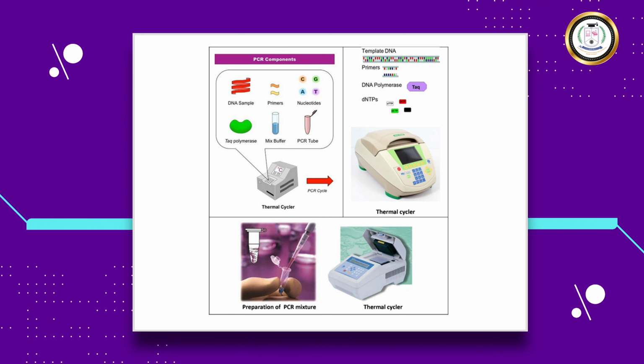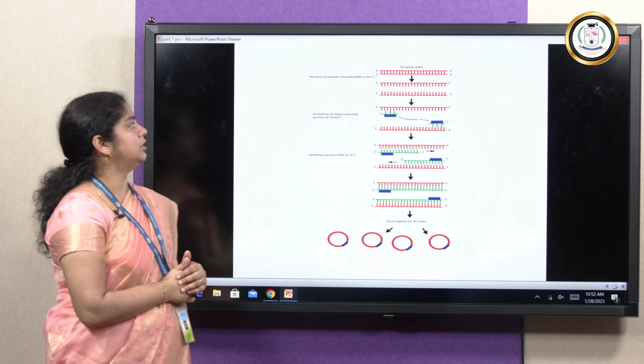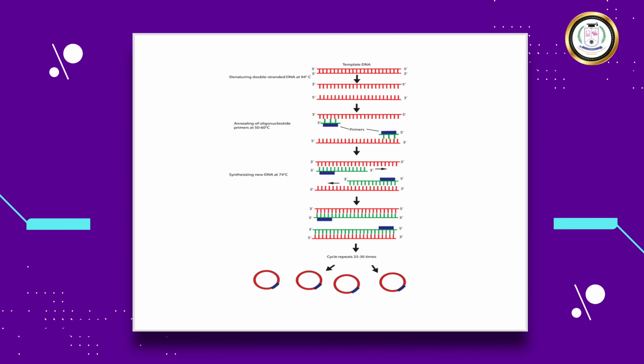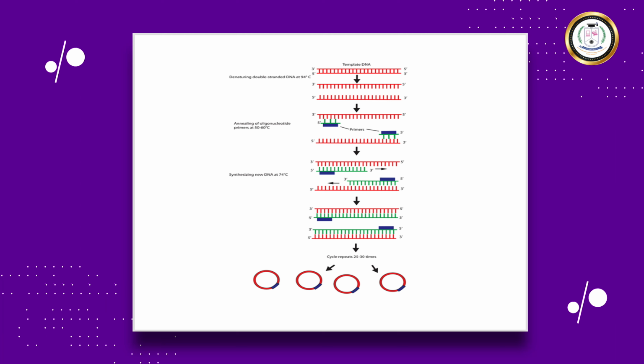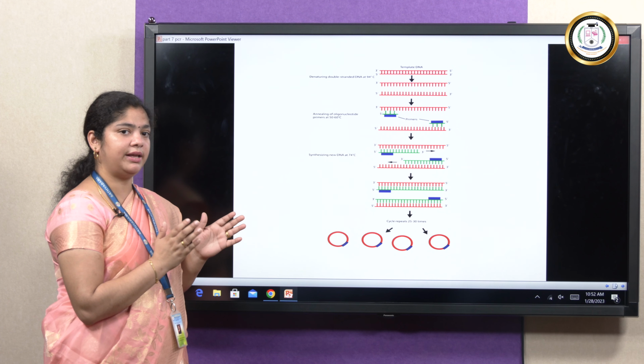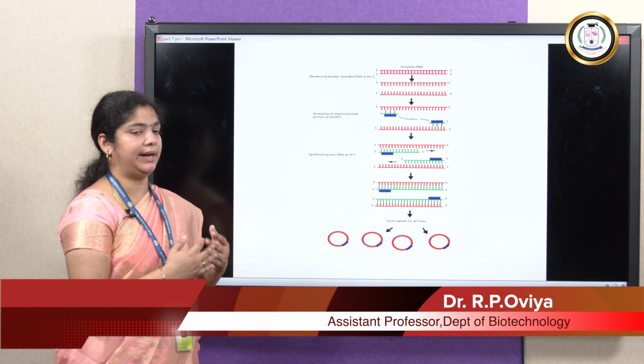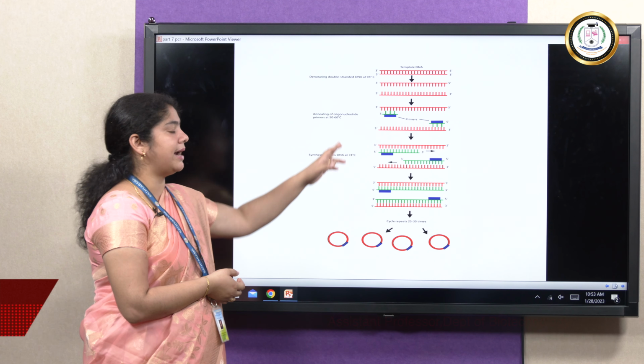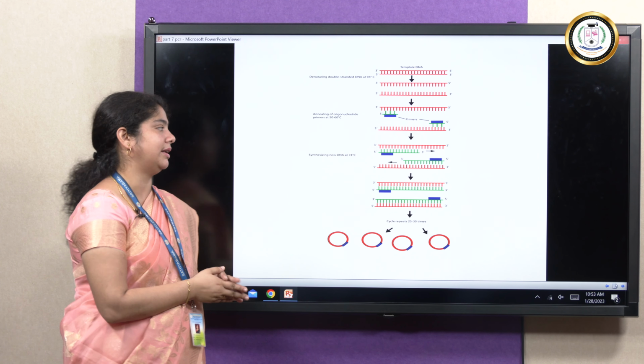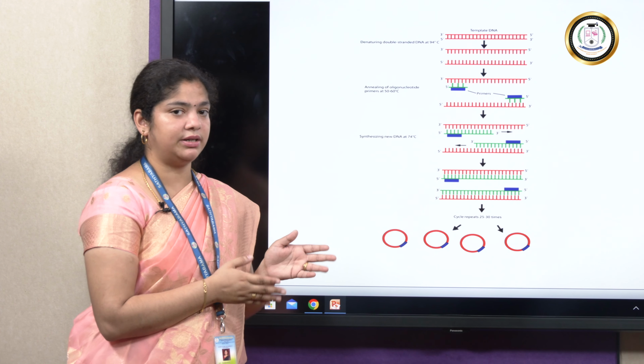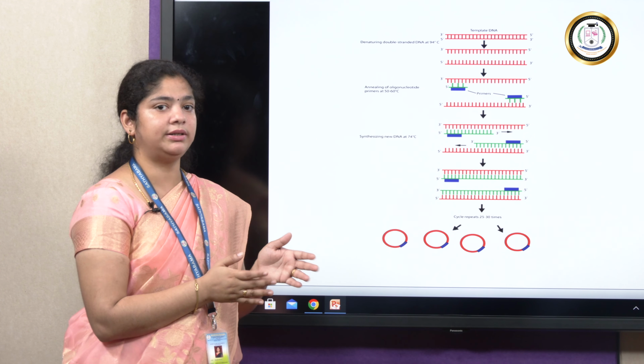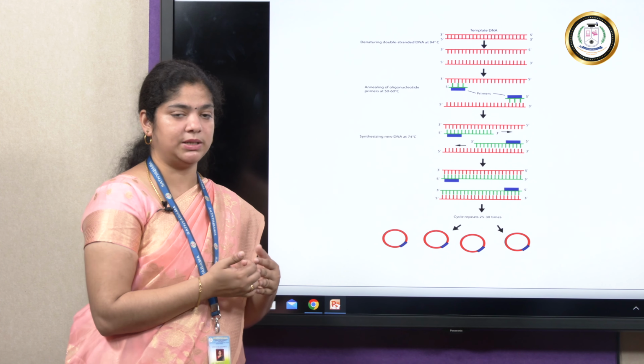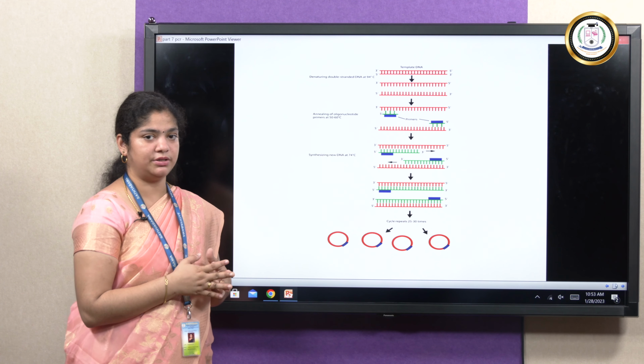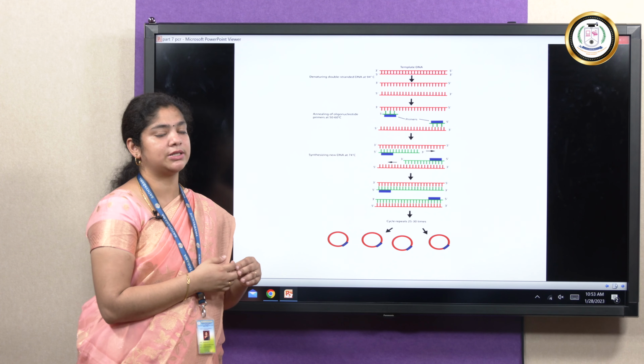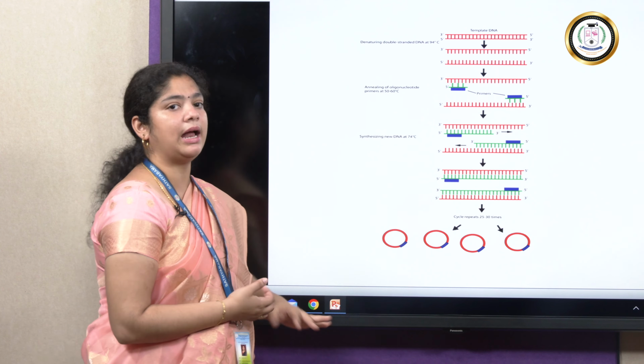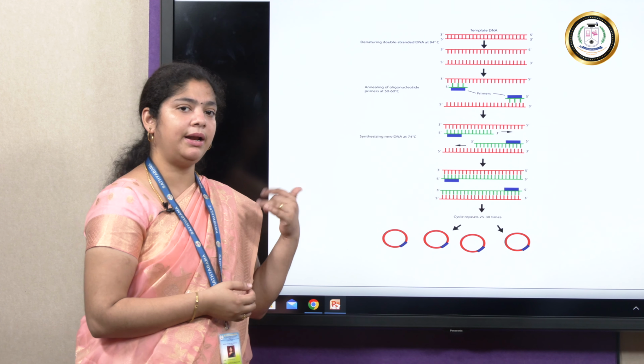This is a thermal cycler, where the PCR reaction is set up. The first step is denaturation, obtaining single-stranded DNA, and then the primer is added, that is annealing. The annealing temperature varies from 50 to 60 degrees, depending on the template and the primer, so it has to be standardized for each target gene. Then we need extension at 72 degrees Celsius, which depends on the target size. For 1000 base pairs, one minute of extension is required, whereas above 1000 base pairs the extension time has to be increased. The same cycle is then repeated for 25 to 30 cycles to obtain more amplicons.